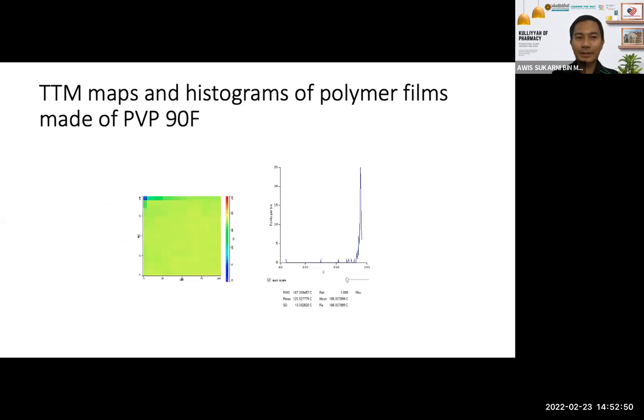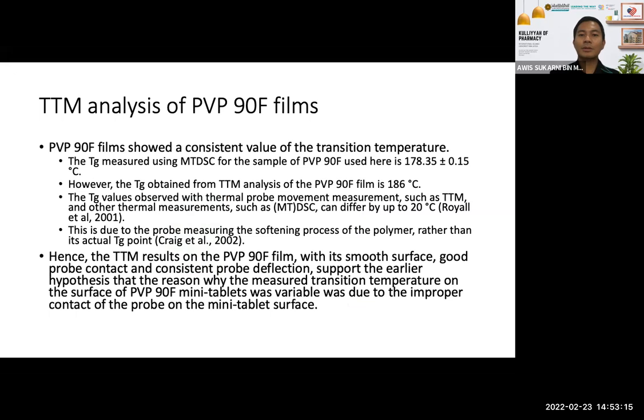And then we move to the PVP90F film. As you can see here, it shows a very nice green color. And when we look at the histogram here, most of the temperatures show a transition temperature at around 186 degrees Celsius. So this confirms the theory that we made before, that they cannot show the actual reading because of improper contact between the probe and the surface of the sample. And based on the MTDSC result, the Tg of the PVP is actually around 178 degrees, but for the TTM it shows quite high, 186 degrees.